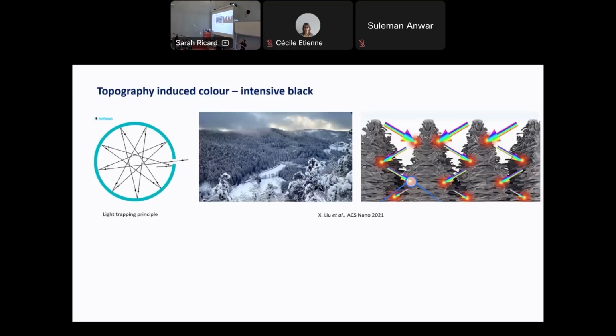To do an analogy, we have a landscape where we have flat views, and then it's always darker in the forest. And then we can engineer these concepts on our metallic surfaces. We do that on a micrometer scale, of course. This is a representative multi-scale surface topography in micrometer scale. You have this in micrometer. They are a micrometer forest, if you want, trees. On the top of the trees, there's a second scale: smaller branches, twigs, leaves, and so forth. They are nanoscales.